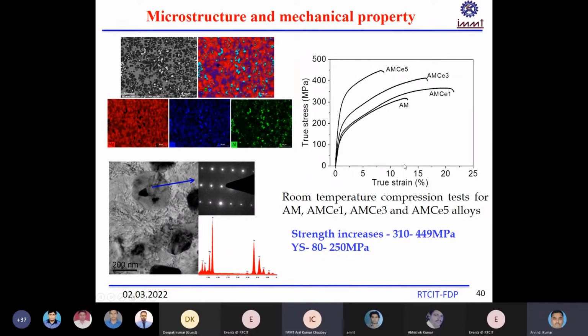It was earlier around 15%, but it is going around 25%. But if you are increasing cerium further, you are reducing the ductility. So if you want a high ductility around 25%, then you can use only 1% cerium. But here strength is a little more compared to the magnesium aluminium. But if you want to increase the strength further, you can improve the cerium percent to around 3%, but here the ductility you are getting is around 17 to 18%.